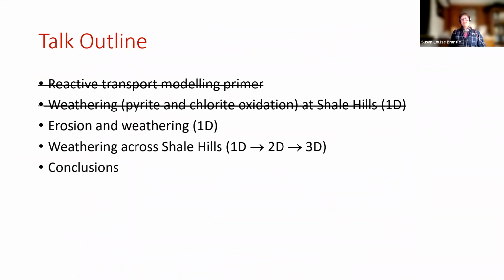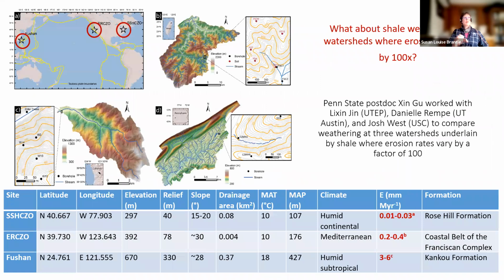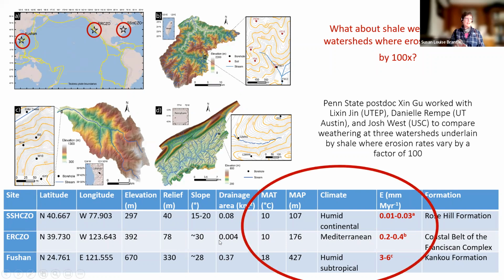All right, so if that's true, we should be able to see the oxidation rates much faster in more quickly eroding systems. And so we did, we looked across some shales weathering and eroding at different rates. So here's Shale Hills. And then we went to another CZO in Eel River, Northern California. And then we worked with Josh West, who had samples from Taiwan. And they're all shales and they're all weathering. And here's the data for the different systems: Shale Hills, California, and Taiwan. And it's not a perfect experiment. The erosion rate is 100 times faster in Taiwan, and it's 10 times faster in California. But the temperature changes to some extent, and the precipitation is also faster in Taiwan. But by far the biggest change is in the erosion rate.